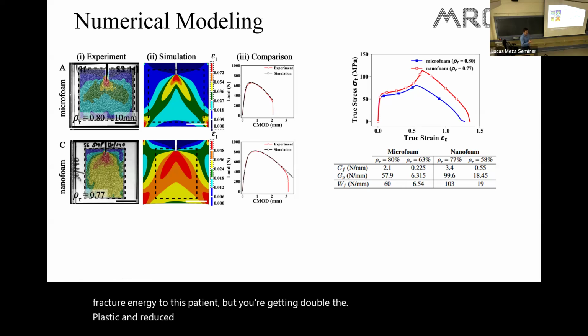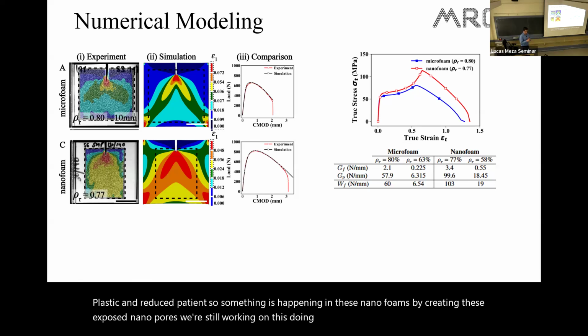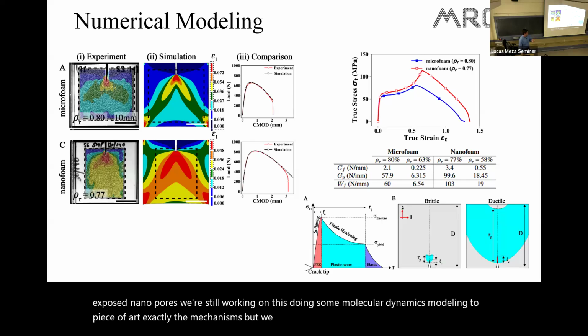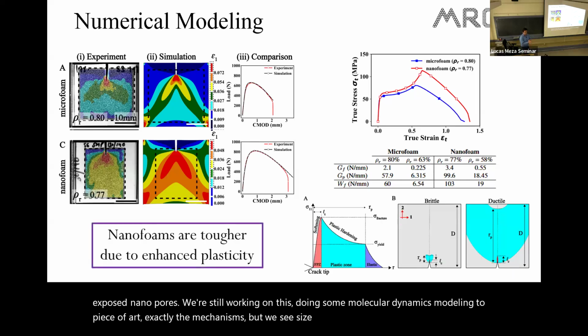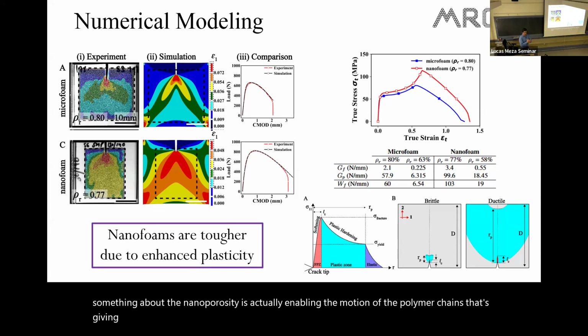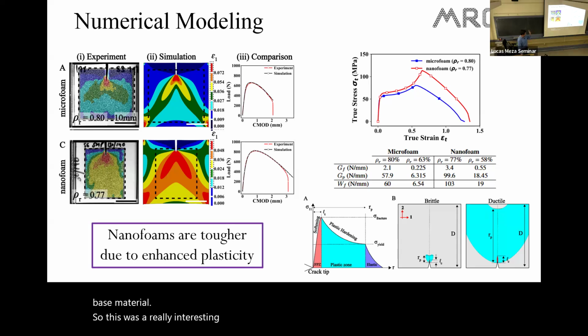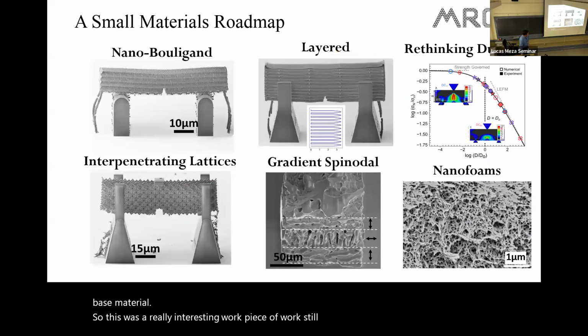So something is happening in these nanofoams by creating these exposed nanopores. We're still working on this, doing some molecular dynamics modeling to piece apart exactly the mechanisms, but we see size enhanced ductility of that nanofoam. Something about the nanoporosity is enabling the motion of the polymer chains, giving us much higher plastic energy dissipation, in some cases exceeding that of the base material. So this was a really interesting piece of work, still ongoing.